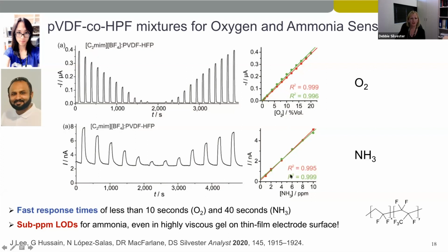And the response times were very quick. Oxygen had a response time of about 10 seconds, and ammonia was about 40 seconds. Very importantly, we could easily detect less than 1 ppm of ammonia, which is very important for detecting this toxic gas in real environments. So although we have this gel polymer electrolyte, we can easily detect these low concentrations.